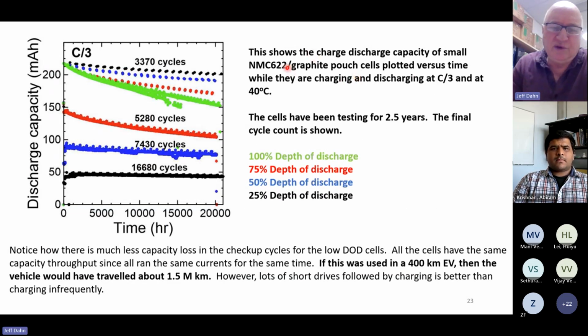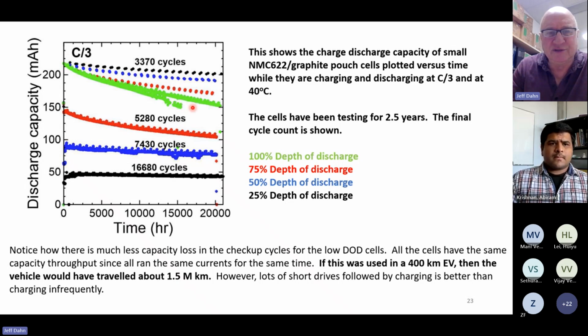So here's some data that one of our students, Roby Gauthier, collected. This is showing discharge capacity versus time. Cells are being charged and discharged at a 3-hour charge and a 3-hour discharge. And these are NMC 622 graphite cells. The green cells are being cycled between 4.1 and 3 volts, 100% depth of discharge. The red are 75% depth of discharge. The blue are 50, and the black are 25% depth of discharge. So you can see the discharge capacity scales with the depth of discharge range, as you expect.